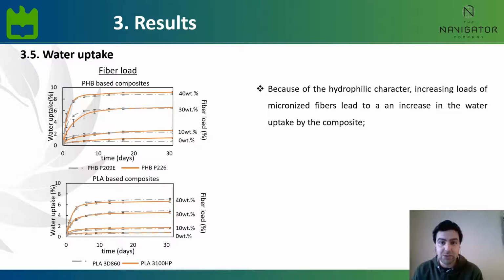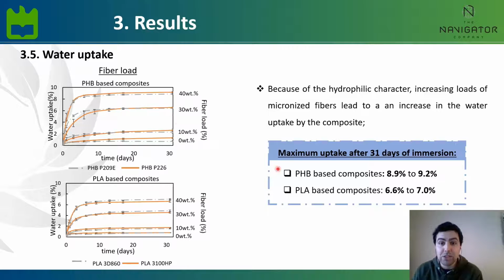Now looking at the water uptake results performed by immersion during 31 days, we see that all thermoplastic polymers, PHB and PLA, have lower water uptakes, which is easily justified by their hydrophobic nature. But on the other hand, cellulose fibers are hydrophilic, and so as the fiber load increases, so does the water uptake, as expected. It is worth noting that PHB-based composites have maximum water uptakes higher than the PLA-based composites, which is also probably related with the inferior compatibility between the PHB and fibers that makes it easier for the water to flow inside the composite.